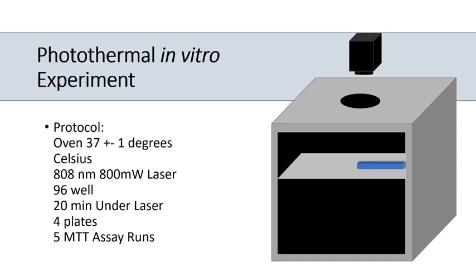So we get into this experiment now. And this experiment has to be run as quickly as possible because we're irradiating 4 wells per plate that we use. And so it's 20 minutes per well. And then there's also time in between when you're filling with the sample, when you're putting it in, when you're cleaning it off, and when you're changing it in the oven.